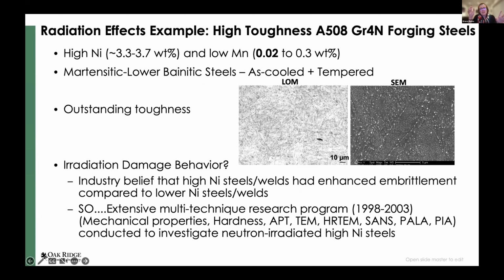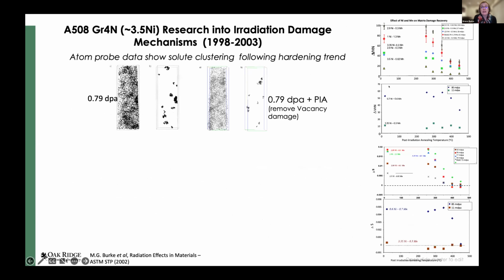Well, what I'm going to show you is some interesting things. The nuclear industry believed that high nickel steels and weldments exhibited enhanced embrittlement. So nickel was viewed as a bad actor. And we had an extensive research program to look at the whole picture on neutron irradiated high nickel steels. With early atom probe tomography data, it was possible to detect these solute clusters and analyze them, but also to post-irradiation anneal these specimens to eliminate vacancy-related damage. And again, we could do hardness and positron annihilation analyses.